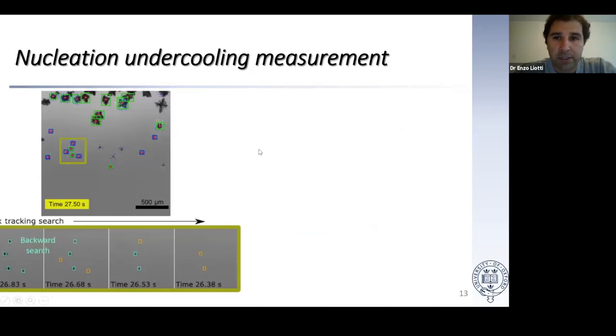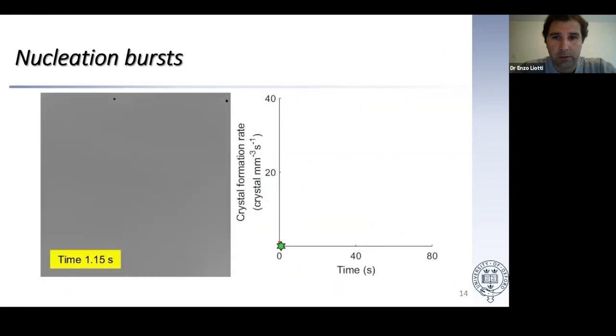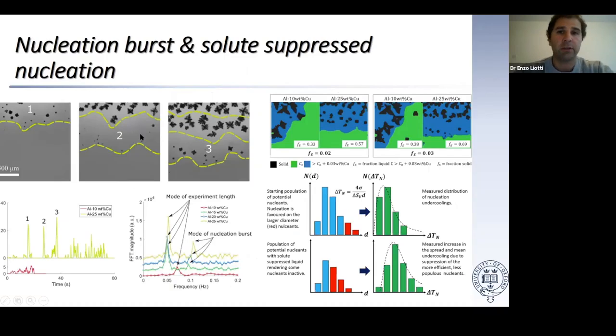We believe that all of this is related to this explanation here, and to how the undercooled zone is developing. The undercooled zone is how much driving force there is in the liquid that is not yet solid. So the undercooling drives both the growth of the grains and the nucleation of the grains, and there is a balance between them, depending on what we call solute suppression. When you have a mixture of solid and liquid, some of the solid that is forming is growing, but in growing it is ejecting solute. In this case, it is the blue. In an alloy richer in solute, this blue area, for the same solid fraction, is higher than when you have less solute.